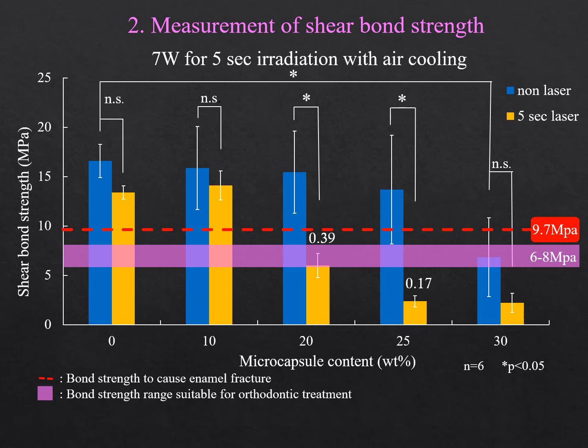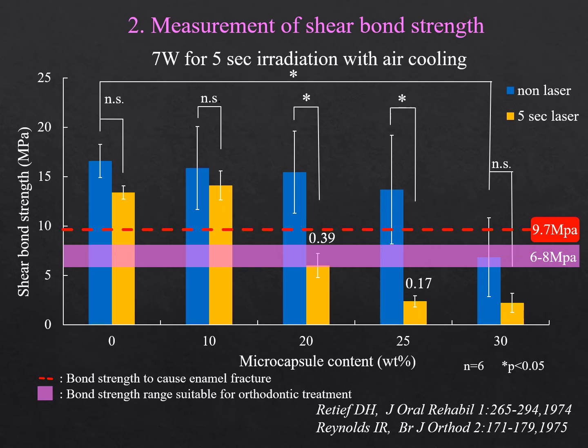The results of the shear bond strength of the irradiation and non-irradiation groups are shown. The blue column is the non-irradiation and the yellow column is the irradiation group. It is reported that the red dotted line with a bond strength of 9.7 MPa may cause enamel crack when removing brackets, and the purple band of 6 to 8 MPa is suitable for orthodontic treatment. In the group containing 0, 10, and 30 weight percent microcapsules, no significant difference was observed. However, in the groups containing 20 and 25 weight percent, the shear bond strength decreased significantly in the laser irradiated group, which was 0.39 and 0.17 times compared to those in the non-irradiated group.